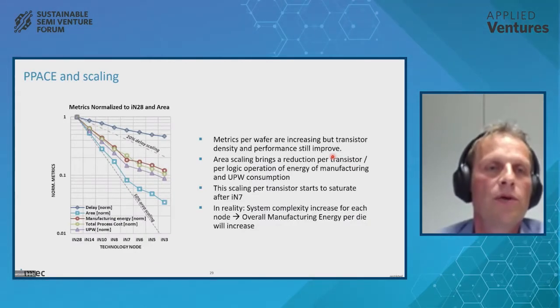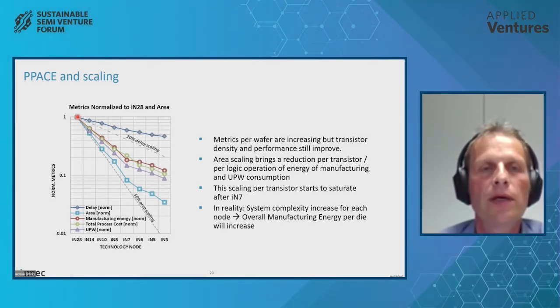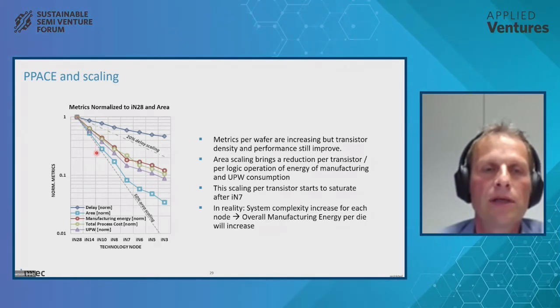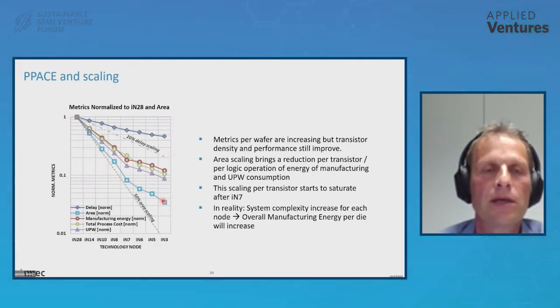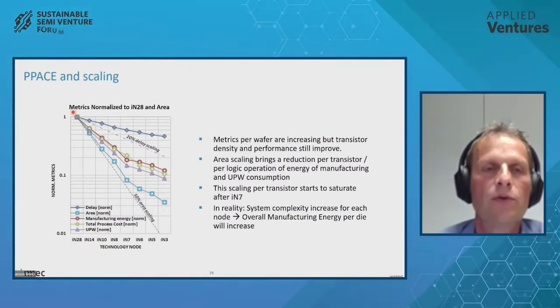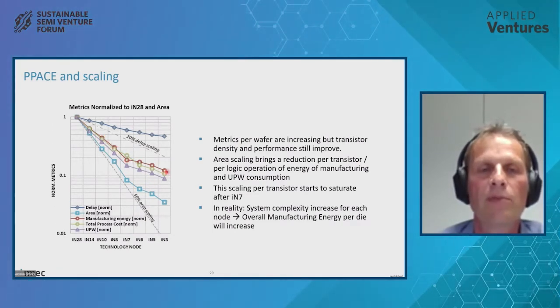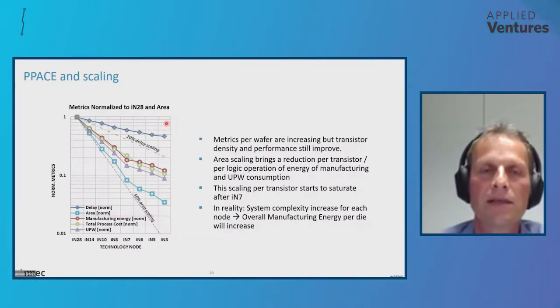Finally, when we look at normalizing these metrics to an area and to the 28 nanometer node, putting that at 1, and then looking at how it progresses node to node, we see that we are getting improvement in area scaling. It is getting better for each node. And we do see that the devices are getting faster. So there is an improvement compared to the 28 nanometer. We also see that the cost and the environmental costs are also improving node to node. But that's when you normalize it to a device.